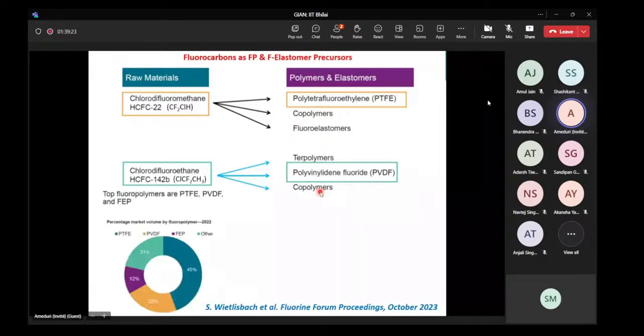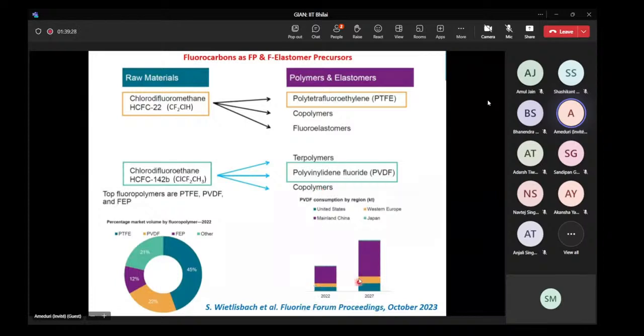So just to mention that the consumption of PVDF is very important. From 22 to 27, the estimation is that it is going to more than double in China, and more than double in Japan, because a Korean company is producing that. In Europe, we have Arkema and Solvay, which are producing, and it is planned to double in 5 years. So as you can see, the production of PVDF will increase a lot. And this may be the reason why it's estimated to be higher than PTFE.